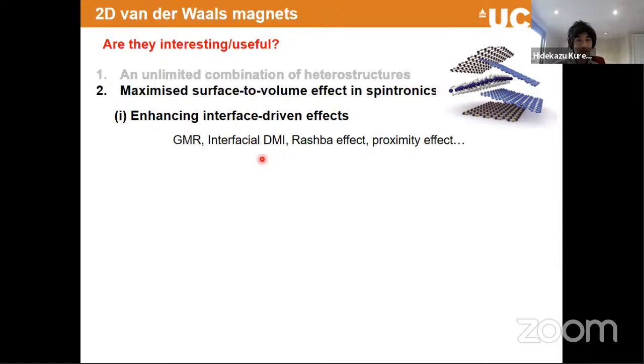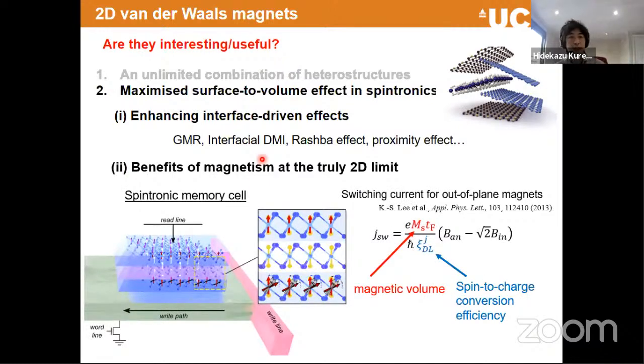Now, looking more application-wise, one of the still exciting applications from spintronics is making memory. So if you think about making memory from 2D van der Waals systems, what we can notice by looking at this simple phenomenological magnetic spin picture describing the switching is how much current density is required to switch one of these layered magnets or moments. Just looking at the numerator side, there is a product of the magnetic moment and the thickness. Again, if you are able to stabilize this magnetism in truly 2D systems, that means we can minimize this thickness. And also typically it doesn't have a very large magnetic moment.